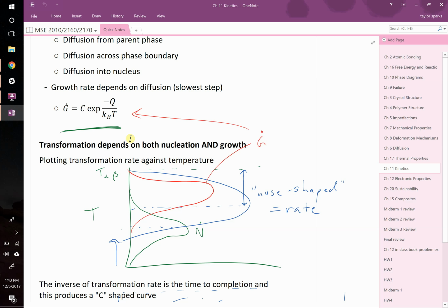Yeah? And I just touched on this, but just to clarify, when do you tend to get a lamellar structure as opposed to precipitate pockets? Lamellar occurs when you're forcing a reaction to go from a liquid to two different solids, or from one solid to two different solids at a single temperature. Basically, if you make it happen slow, then they're not able to segregate out and form big grains with less surface area than these little zebra stripe things. But if it has to happen fast, that's what leads to this lamellar structure. So eutectoid temperatures and eutectic temperatures, that's where you see those.